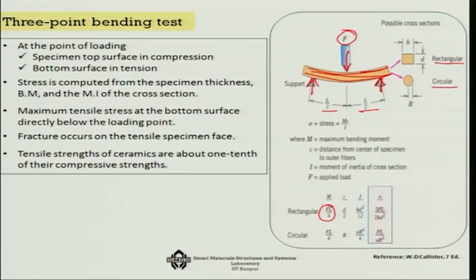So, this FL by 4 is the bending moment that the specimen is subjected to, and if I know this bending moment M, and if I know where exactly a particular fiber is located, for example an extreme fiber at distance y, then the stress is My by I. So, I can find out what stress it is subjected to. Thus, from the 3-point bending test, by finding the bending moment and using the sample geometry, we can find the compressive stress and the tensile stress that the sample is subjected to.